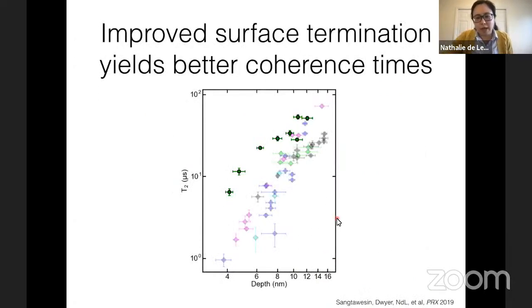So just to give you the headline result, after doing all of this processing, what we're able to do is improve the coherence time of shallow NV centers. This is these dark green points here by basically an order of magnitude at the same depth. Okay, so now if you don't want to hear about surface spectroscopy, you can just fall asleep for the next 10, 15 minutes, but I'll basically just go through the different pieces of evidence that we have for these different surfaces.